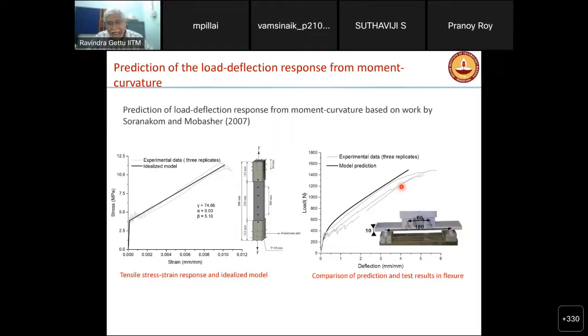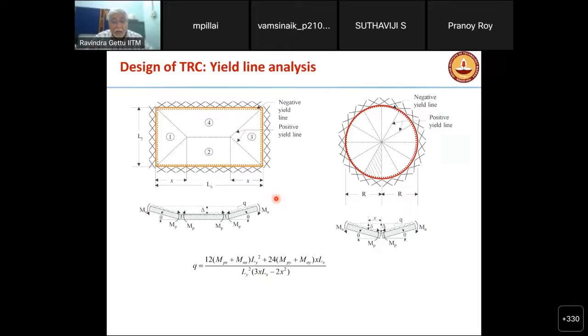Right now it is on the upper bound, but we have to work on it a little bit more. The light gray curves are experimental curves, and this top one is the prediction made from this. So we do a tension test, get the model, and use the tension test to predict what happens in bending or some other element. So we've been progressing a lot here. Now to larger elements, we can use yield line analysis. The textile is going to help in the rotation capacity. And we know that when there is rotation possible, we can use yield line analysis.